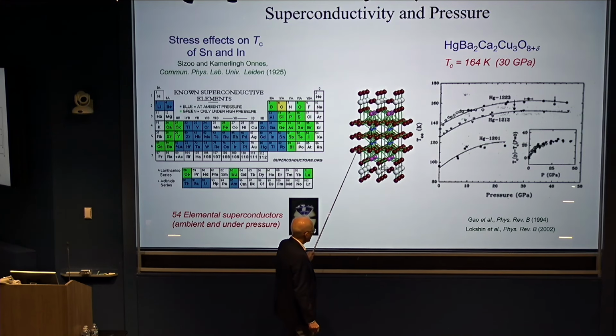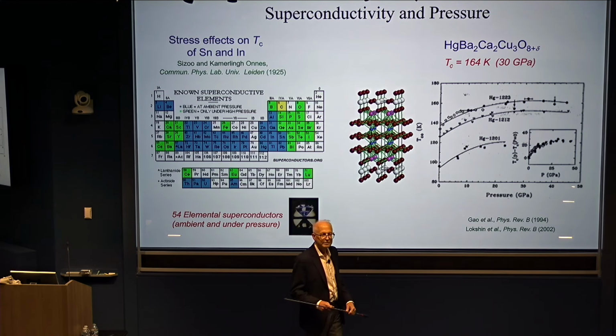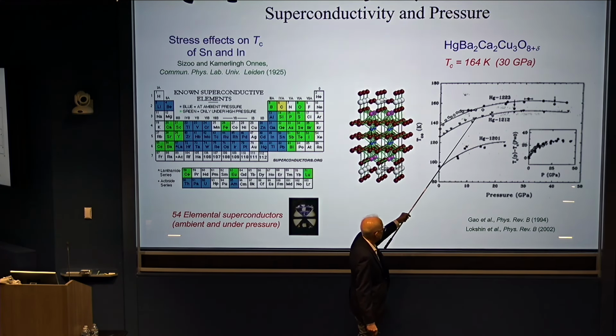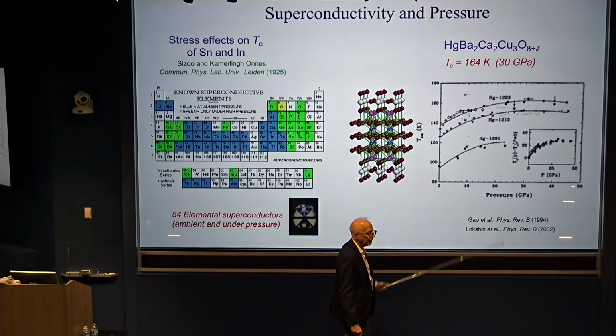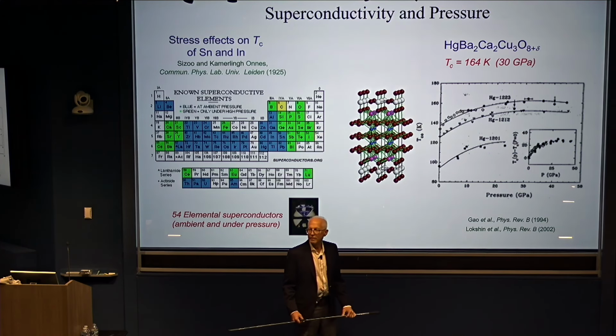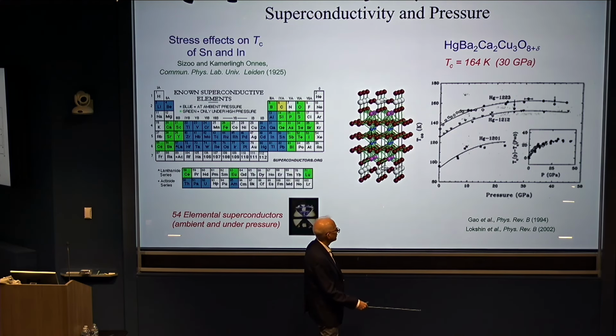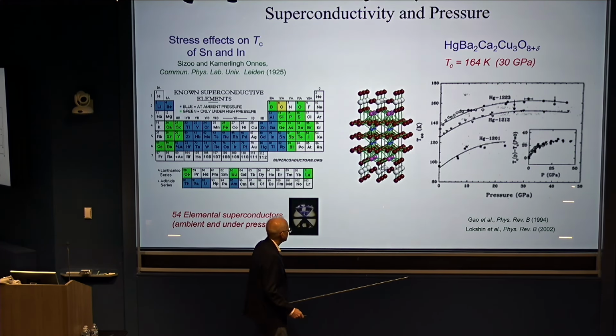This was announced with great fanfare at the Woodstock of Physics many years ago here in New York City. This was the highest TC superconductor measured under pressure, this mercury-bearing compound, and until the discovery of the hydrides, had the record for the highest TC, and I'll come back to this in a few moments. So what about hydrogen and its metallic character and its possible superconducting character?